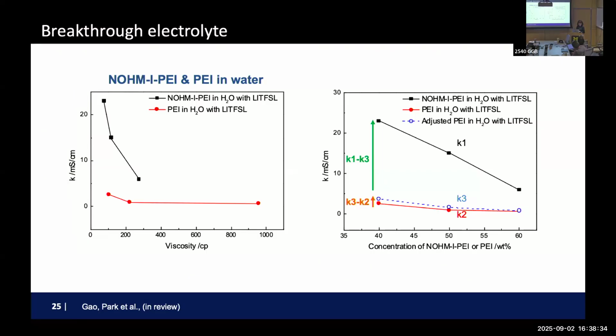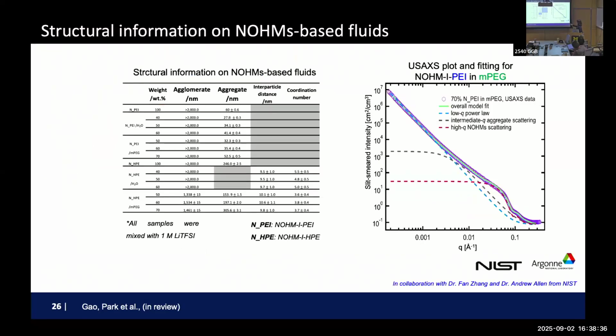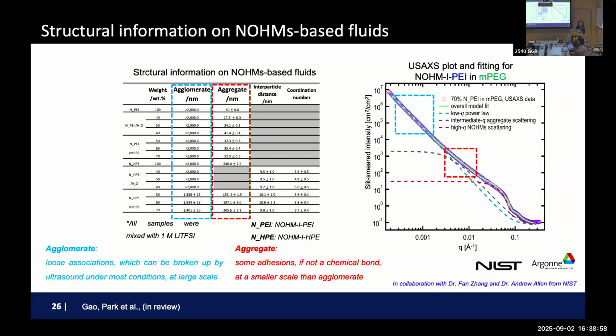So we actually took this to Argonne National Lab. And if you're familiar with USAXS, this is not SAXS, USAXS data, where Q is the inverse of the length scale. Whenever you work with nanoscale materials, you have a lot of signal at the high Q range because that's nanoscale. Usually you don't get signals at the low Q range, which is chunkier stuff. But as you can see, we have much of the chunkier stuff.